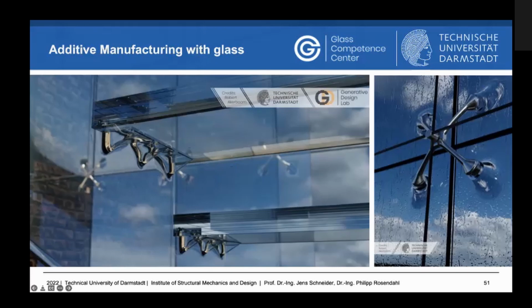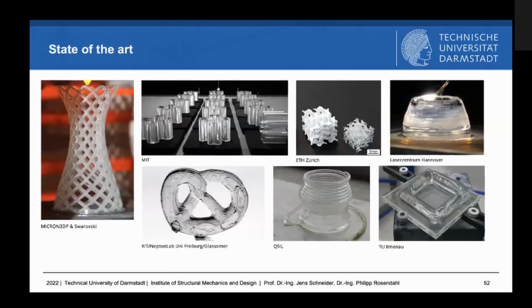On the right-hand side, you see a glass facade where the different glass panels need connectors. And in order to make these connectors structurally powerful and very strong, we'd like to avoid the typical drilling through the glass that is necessary, or the addition of adhesives on top of the glass surface for the connection, because every processing step that you do with the glass, every subtractive processing step that you do with the glass, introduces micro cracks that weaken the overall effective strength of the structure, and 3D printing could really reduce the subtractive operation steps on glass.